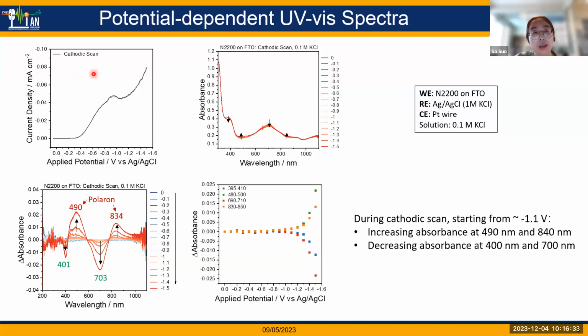And this is the real-time CV that we captured during the potential dependent absorption spectra measurement. And from the absorption spectra, we can already see there are some absorption feature changes. And if we look at the difference absorbance spectra, we can see that we basically captured the similar thing. We saw after negative 0.9 volts, there are two peaks growing, which are the peaks that they assigned to the monopolaron peak. And we also see the decrease of the neutral N2200 peak, which can also be seen by the potential dependence of absorbance figure over here.